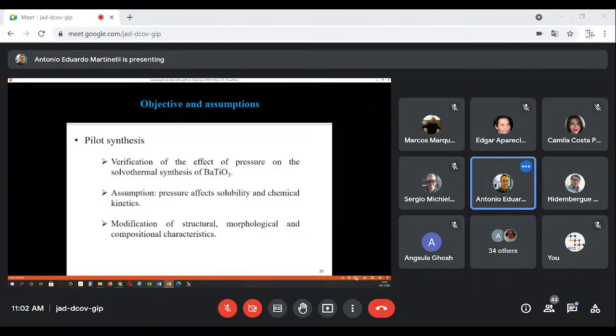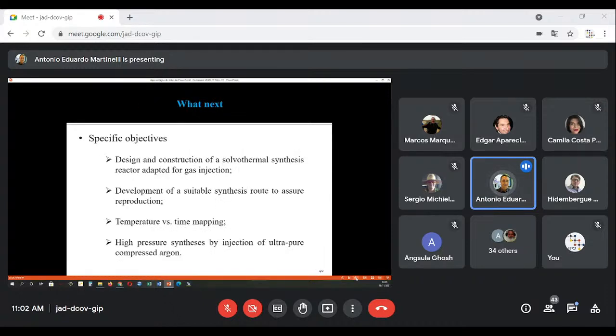The pilot synthesis aimed at verifying the effect of pressure on the solvothermal synthesis of barium titanate, under the assumption that the pressure affects the solubility and the reaction kinetics, and therefore we might expect changes in composition and changes in morphology. The specific objectives of the work were to design and build a solvothermal synthesis reactor adapted for gas injection, to develop a suitable synthesis route to assure reproducibility in the case of barium titanate, to map the temperature and time progress of the morphology and composition, and to apply external pressure to investigate high pressure synthesis by the injection of ultra pure compressed argon.